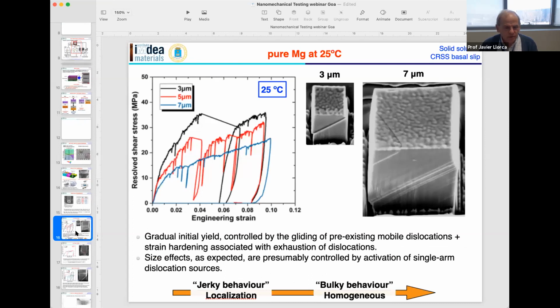This is the results of mechanical test. This is pure magnesium. This has been tested at 25 degrees Celsius. And these are the resolved shear stress versus engineering strain curves. And these are for micropillars that have 7 by 7 microns cross sections, 5 by 5 microns cross section, and 3 by 3 microns cross section.